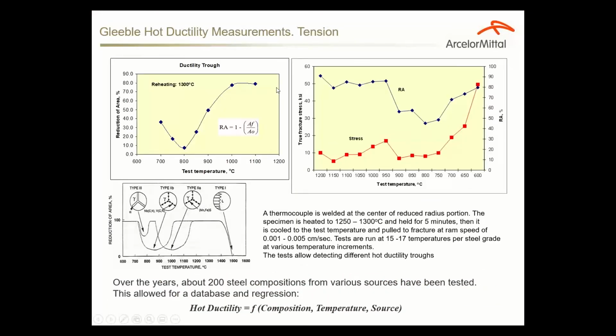Typically, all steels exhibit what we call a ductility trough in a certain temperature area. There are several types of ductility troughs when the slabs are cooled, and those troughs, those regions of very low ductility of cast steels, are related to different metallurgical phenomena, like precipitation, different kinds of non-metallic inclusions and stuff like that. With our ductility measurements, we actually can detect some of the ductility troughs using this reduction of area criterion. We can also measure the stress at fracture and its temperature dependence.